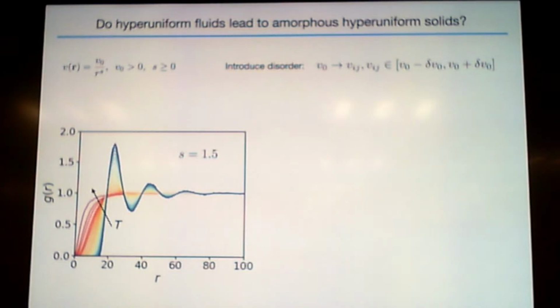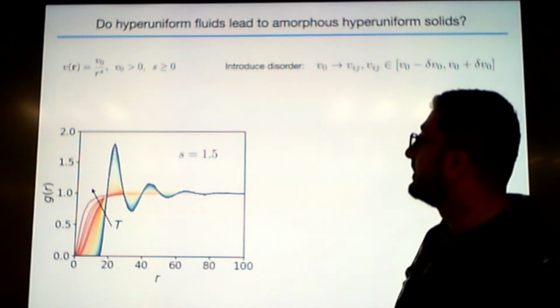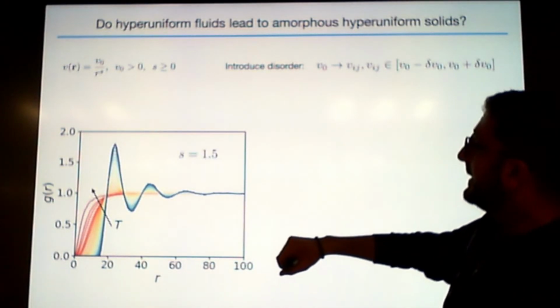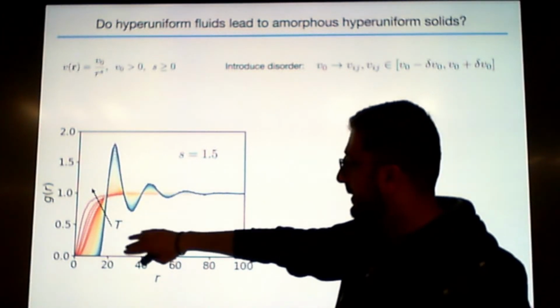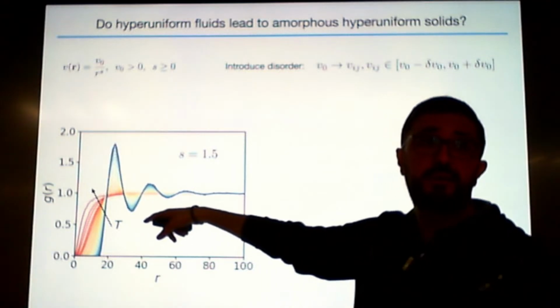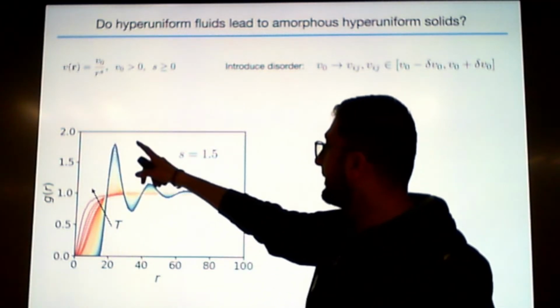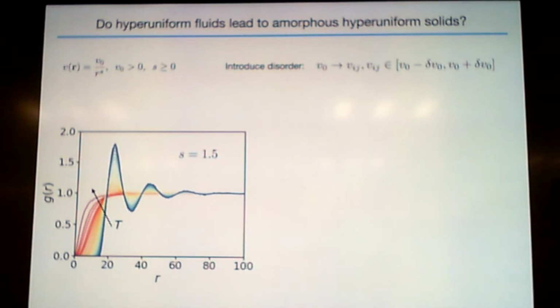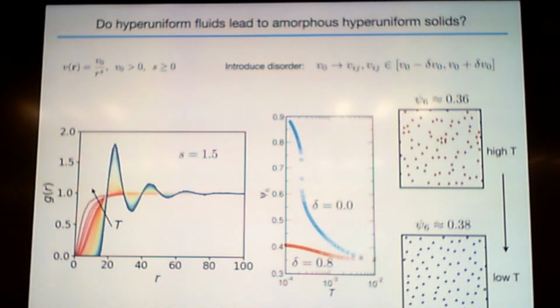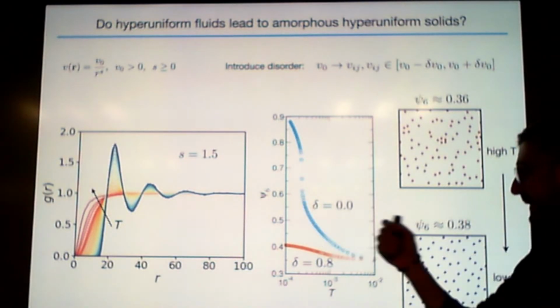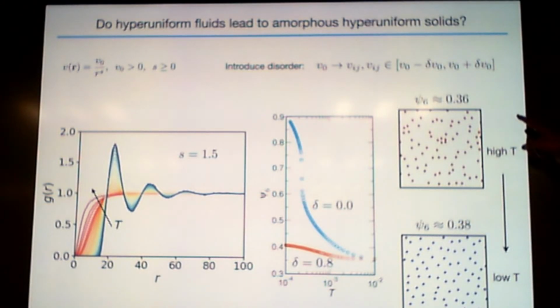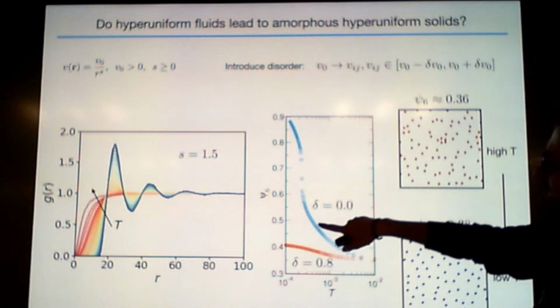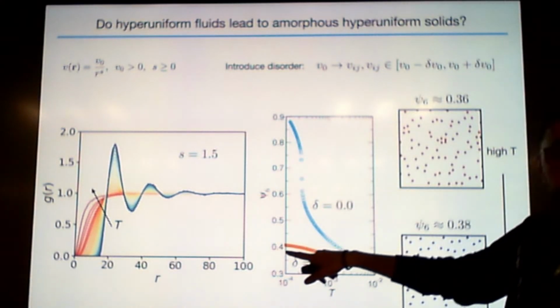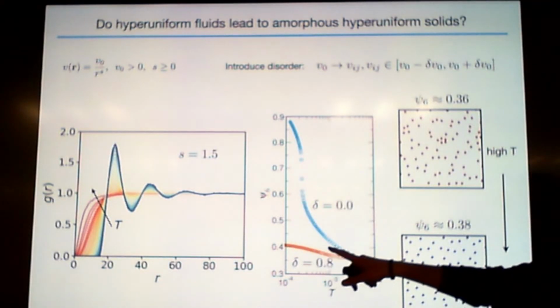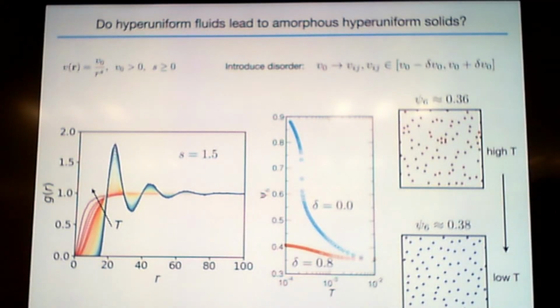Okay, so this is the pair interaction, pair distribution, pair correlation function, G of R, for a specific value of delta. At high temperatures, there's almost no structure, and then the most blue one is the zero temperature, frozen one, basically. You have this liquid-like shell structure at zero temperature. Then we also measured psi 6, the bond orientation order parameter, at high T, and we go all the way to zero T. And without disorder, you have a phase transition to crystal. With disorder, not much happens. Or maybe something happens, but we can't resolve what's happening here. So we can't say where the glass transition is here. Not yet.